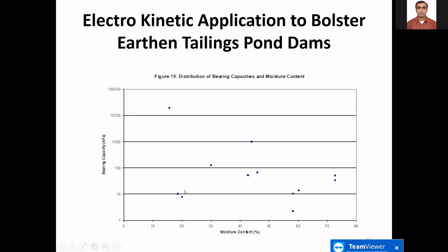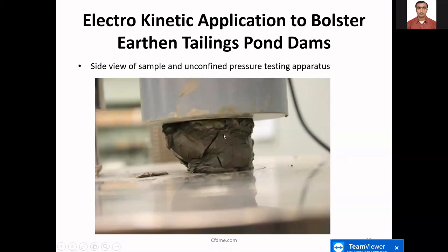on hitting 10 kPa. This sample up here, I was just basically doing for fun. I wanted to see how hard I could make this material, essentially a rock. This is a picture of a core of the treated tailings material in these unconfined compressive strength tests. And you can see the planes of weakness that occurred as you applied the force. So it looks quite plastic, and it is quite plastic, at least for the first few days after treatment.